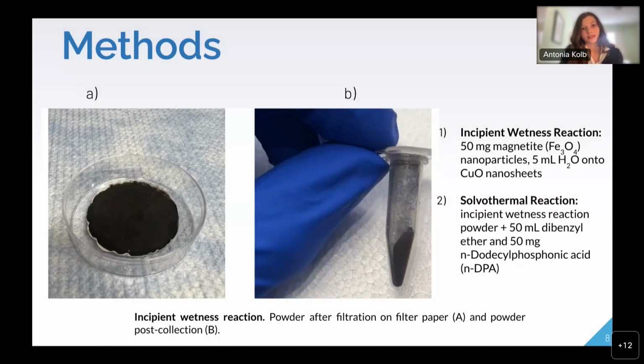Now, using the incipient wetness reaction, I was able to deposit the Fe3O4, or magnetite, and deionized water dropwise onto the copper oxide nanosheets until it turned to a liquid consistency. Now, this allowed for the powder to be magnetic due to the ferromagnetic properties of iron oxide nanoparticles. I then heated the previous powder with dodecylphosphonic acid and dibenzyl ether to make the powder hydrophobic.